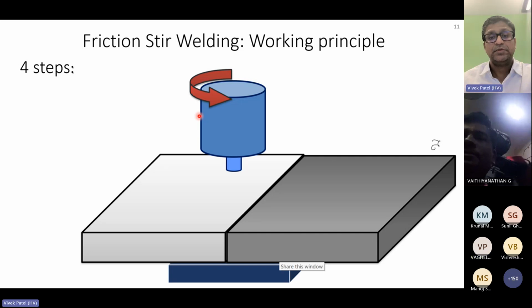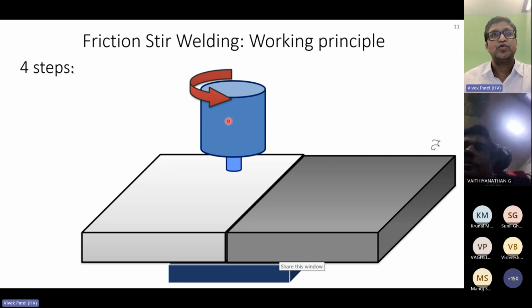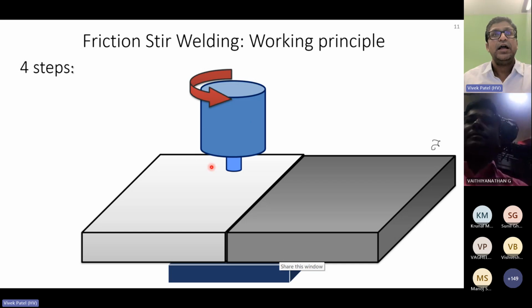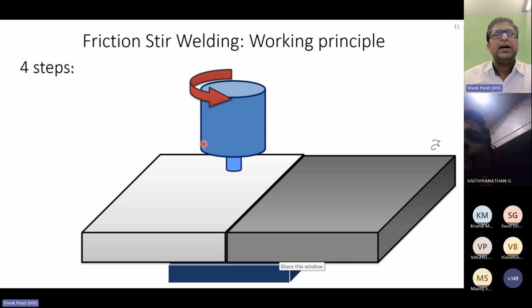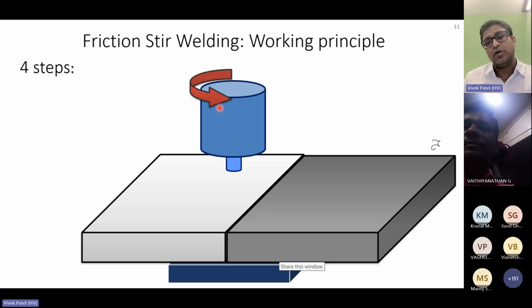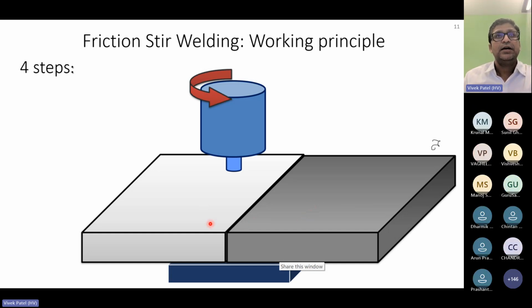And you see that the tool has a shoulder. The shoulder is the larger diameter, and the probe is the smaller diameter. And this tool is driven through rotational energy, clockwise or anti-clockwise, depending. And then this is the example of a butt joint. So you have one part and a second part, and these parts are to be welded.